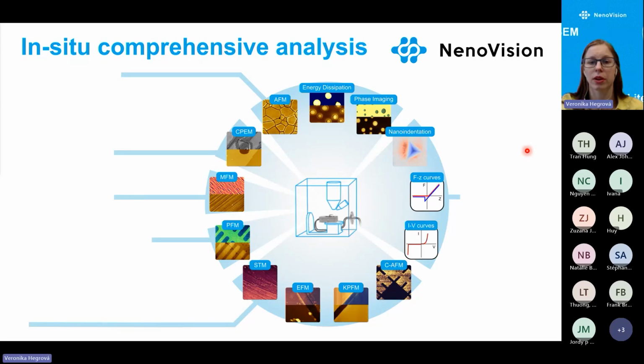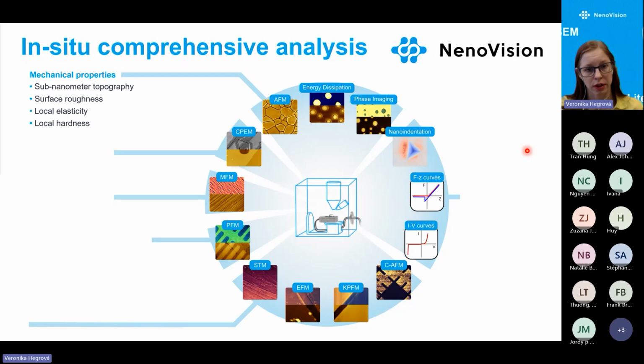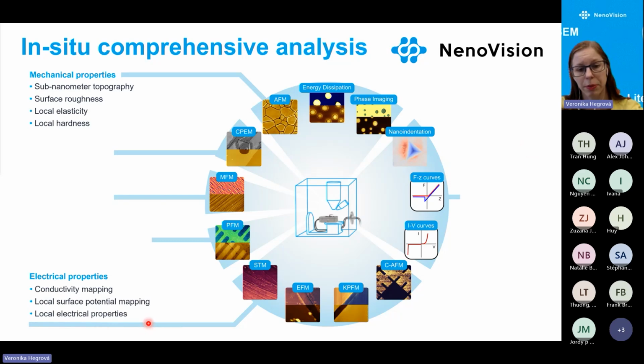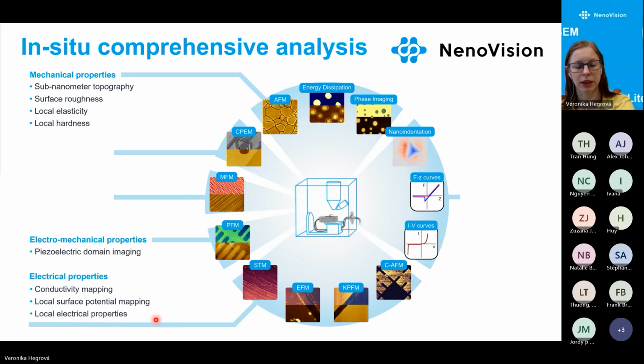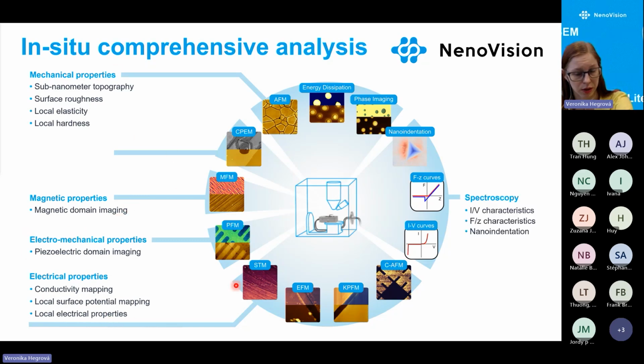Regarding the techniques, so there are several different techniques. I would divide them into 4 groups. So mechanical properties, sub-nanometer topography, surface roughness calculation, local elasticity, hardness can be analyzed from electrical properties, conductivity mapping, local surface potential mapping, local electrical properties. We can measure piezoelectric domains by piezoelectric force microscopy, magnetic domain imaging. Then all of these techniques we can analyze in the spectroscopy mode, IV curves, force distance curves, nanoindentation, or time spectroscopy. And most of these techniques make sense to correlate with the SEM. So all of them can be combined and compared what we see and what we understand is happening.